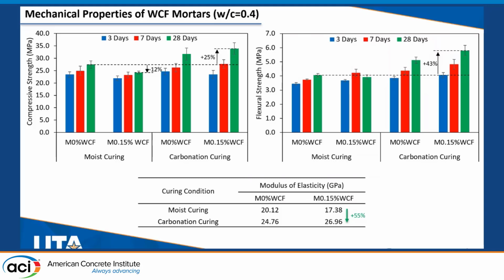You can see here for compressive strength and flexural strength, especially at 28 days, we have reductions in the mechanical properties for moist cured samples. That is completely compensated for after carbonation curing, resulting in 25% enhancement for compressive strength and 43% improvement for flexural strength. Having the modulus of elasticity calculated for carbonation cured samples, not only did the results not decrease, but also a 55% enhancement was observed relative to the corresponding moist cured specimen.